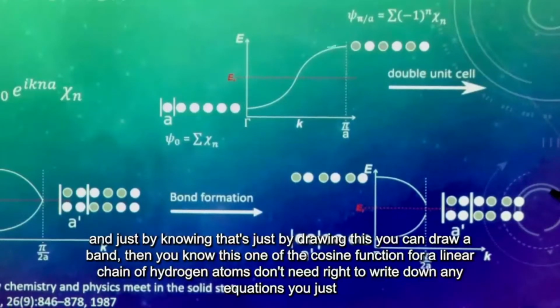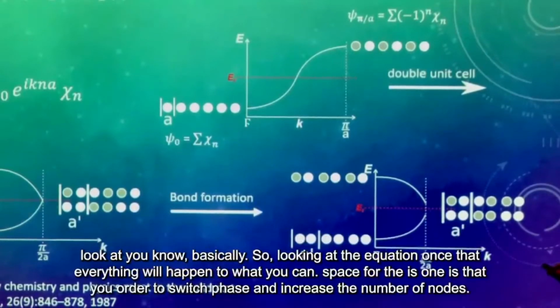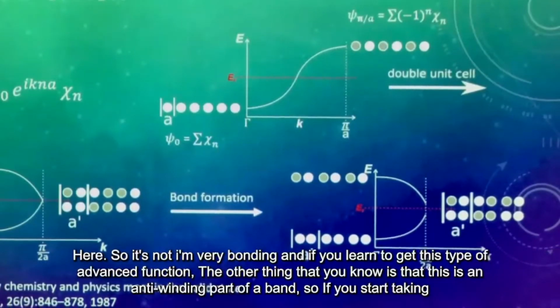And just by knowing this, just by drawing this, you can draw a band, when you know this follows a cosine function for a linear chain of hydrogen atoms. Don't need to write down any equations. Everything that happens throughout your k space, throughout the Brillouin zone, is that your orbitals switch phase and increase the number of nodes here. So you start from very bonding, you go to very anti-bonding, and you get this type of band structure.